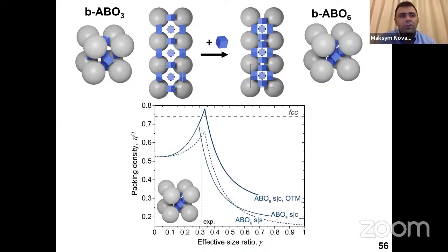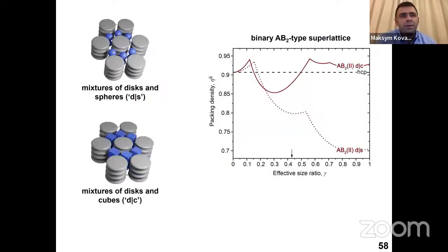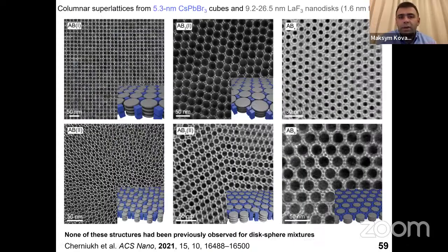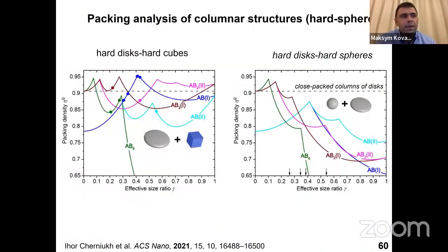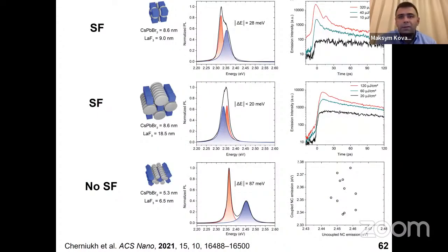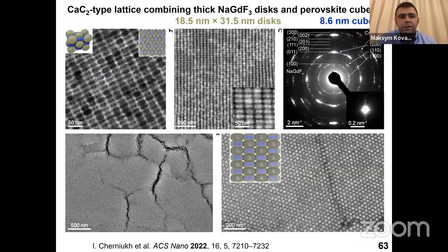And we have discovered a whole bunch of new lattices, which I will skip because of the time matter, but I will just tell you that also when you combine cubes and disks, you again will observe new lattices, which you cannot see when you combine spheres and disks, because these structures have higher packing density. As you can see, for instance, if you compare the space filling curves for this case versus the space filling curve for the sphere disk mixture. And so we have discovered a library of these for different sizes of disks and sizes of cubes. And again, there is a structure property correlation in the